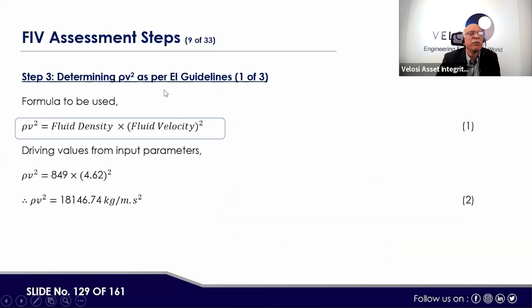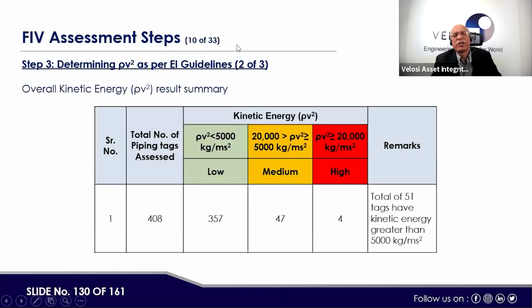Here, how do we calculate this? rho v square, meaning fluid density and fluid velocity, deriving values from input parameters, and this number, 18,146, is greater than 10,000 basically. Then, scale-wise, as per the client requirement, they didn't use the scale of 10,000 kg per meter per second square, they used the scale of 5,000. So all the lines where the kinetic energy calculation is less than 5,000 number 357, between 5,000 to 20,000 kg per meter per second square number 47, and greater than 20,000 were 4. A total of 51 tags have kinetic energy greater than 5,000.